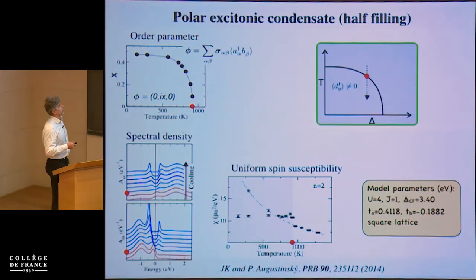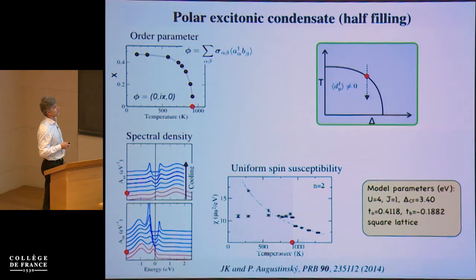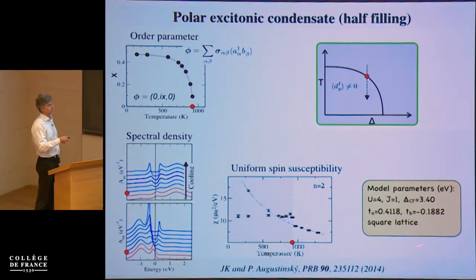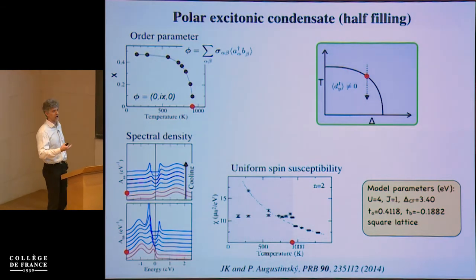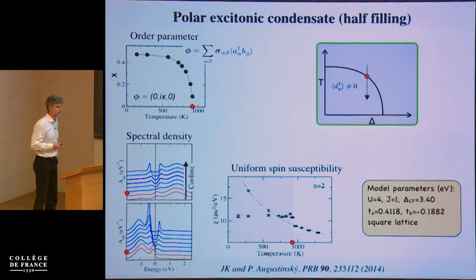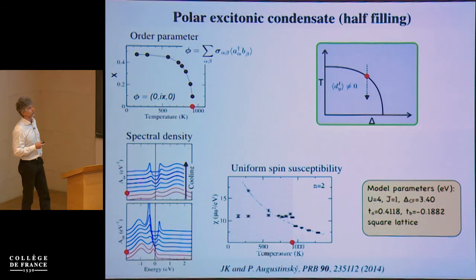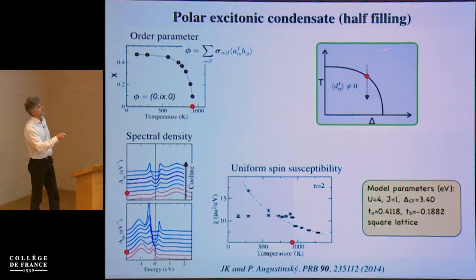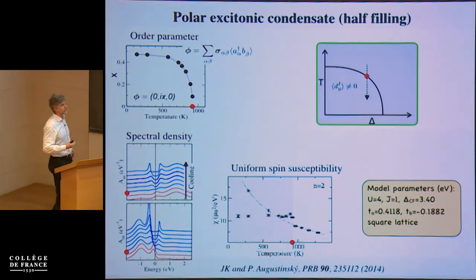So let me start with some results. What I'm going to show you are results for these model parameters on a square lattice. Important is the filling. We are working with the half filling, so we have 2 electrons per site on average, and we are looking at what happens when we cool down from normal phase to a region where we expect this excitonic condensation.